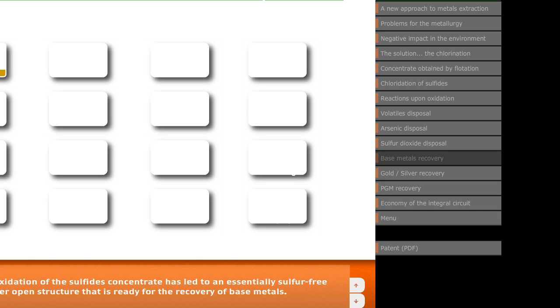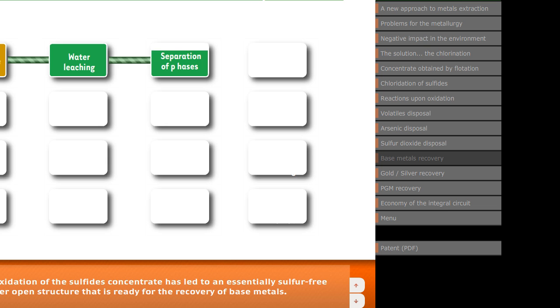The controlled oxidation of the sulfides concentrate has led to an essentially sulfur-free solid with a rather open structure that is ready for the recovery of base metals. The first leaching is done with water in order to recover the soluble sulfates formed during the controlled oxidation. This first leaching is completed by a second one, using 5 to 10% sulfuric acid at 50 to 75 degrees Celsius. These two leachates are combined for metal separation, and the residual solid left is ready for precious metals leaching.